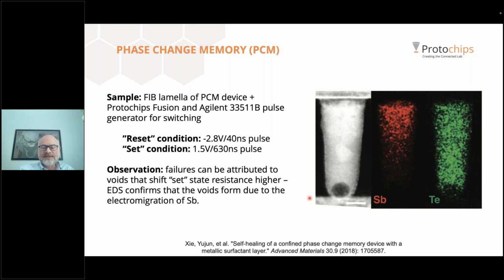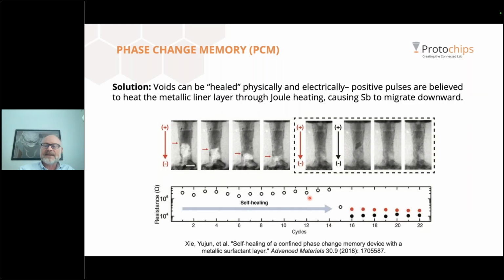And looking at the device in situ reveals why. There's a void. You can see a void in this image. And using EDS shows that the antimony moves away from that bottom junction, leaving a void behind in its place. So the question the researchers had was, can you fix this? Well, the answer is yes.